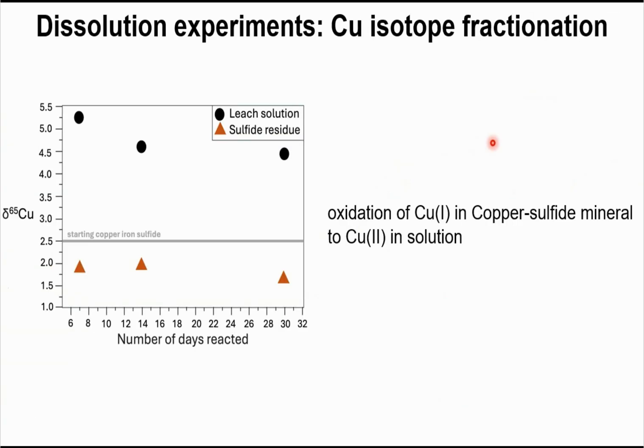Shown here are the results from one of these experiments, where the y-axis, the delta 65 copper, is the ratio of copper 65 heavy over copper 63 light. The gray bar shows you the initial delta 65 copper value for a sulfide mineral, and after putting that into an experimental apparatus, what you can see is that the water becomes isotopically heavy and the residual sulfide becomes isotopically light. And the reason is that copper in sulfides is primarily copper 1+, copper in water is copper 2+.